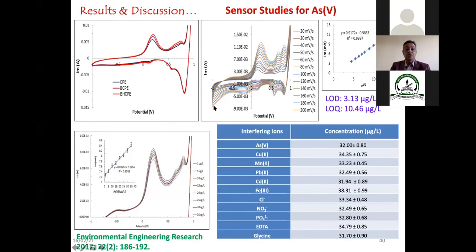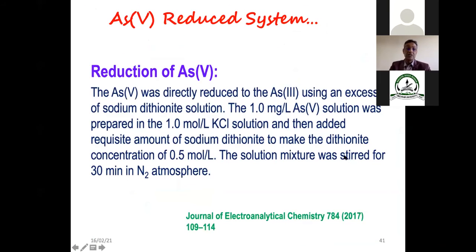This was the data that we obtained for arsenic 5. The problem is that arsenic 5 is not that good electrochemically. It is not being reduced. That is why many reports show that arsenic 5 is not measured directly. They first reduce it using some chemicals and then detect the arsenic 3. But we tried arsenic 5 directly using these materials, and we got quite good results, having an LOD of 3.13.